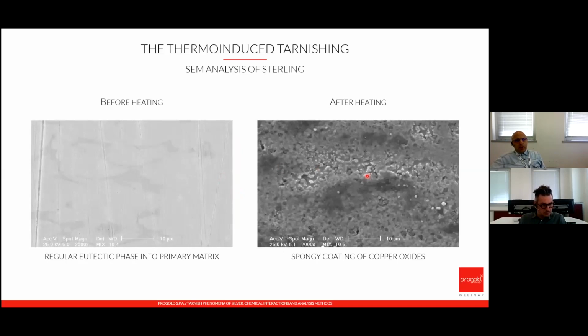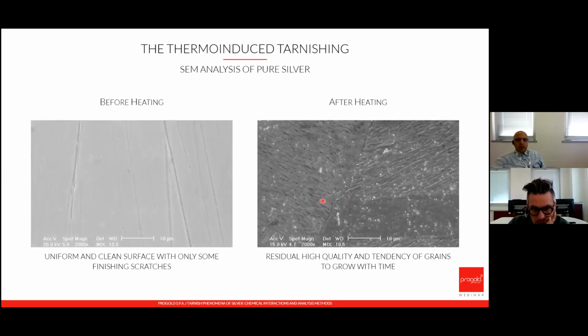The electron microscopy of heated samples at high temperatures revealed, in the case of traditional sterling silver, the preferential transformation of the regular eutectic structure into a spongy copper oxide surface after 6 hours. Whereas in the case of pure silver, as was reasonably expected, we obtain a coarser grain microstructure after thermal treatment, while keeping the very good surface quality of the starting polished condition.